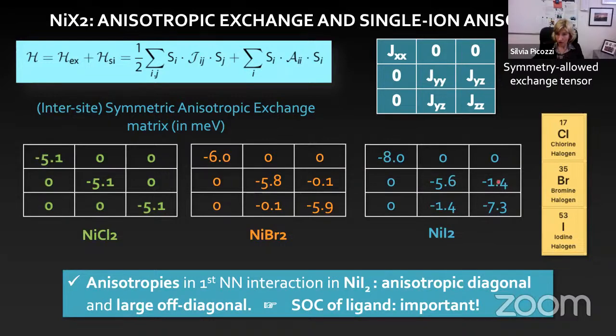So I have strong off-diagonal effects. And you see that because nickel is always the same, if I see some differences, then they must come from the spin-orbit coupling of the ligand. So they must come from, in particular, iodine.